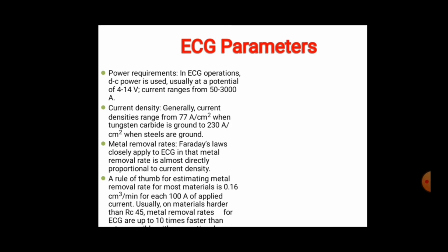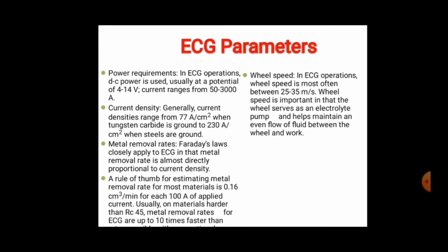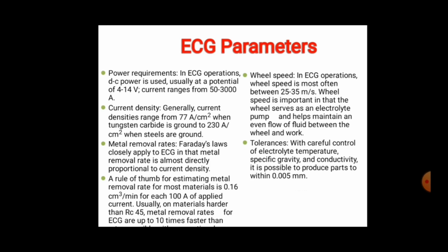Next, a rule of thumb for estimating metal removal rate for most materials is 0.16 cubic centimeter per minute for each 100 ampere of applied current, usually on material harder than RC45. Metal removal rates for ECG are up to 10 times faster. Next, the wheel speed in the system. Wheel speed is most often between 25 to 35 meters per second. The wheel serves as an electrolyte pump and helps maintain an even flow of fluid between the wheel and work. Next, the tolerance. With careful control of electrolyte temperature, specific gravity and conductivity, it is possible to produce a part within 0.005 mm.